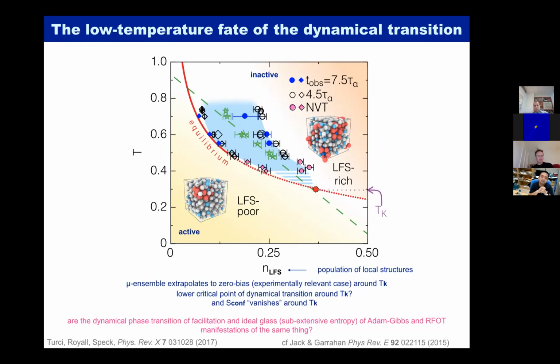If I run out of configurational entropy, then I've only got one configuration. And so there cannot be any two phases anymore if I believe in that picture of the Kauzmann temperature and running out of configurational entropy. So if that's right, I don't see how I can have two phases below the Kauzmann temperature, or there are good reasons that the Kauzmann temperature may not really happen. In fact, there are arguments it's avoided in practice due to thermal fluctuations leading to some kind of diffusion in the material like you have in a crystal. So it may be that that's just not the right interpretation. We just don't have the answer. We can't say no for sure. If one buys the Kauzmann picture, then no, but one doesn't have to buy the Kauzmann picture.